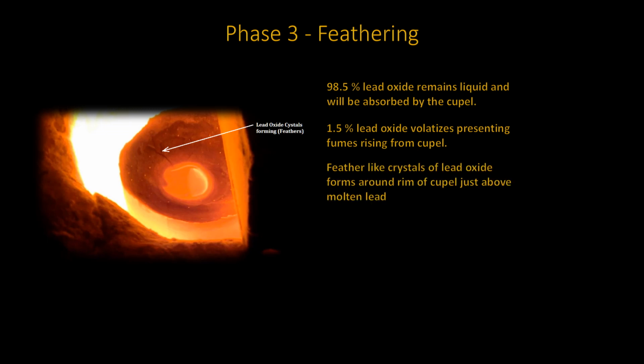If the process progresses correctly, and all things are going well, feather-like crystals of lead oxide will start to form around the rim of the Cupel, just above the molten lead. This is a result stemming from the sublimation of some of the volatilized lead oxide. Feathering is a good indication that the cupellation temperature is just right.